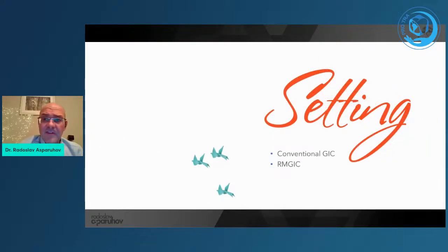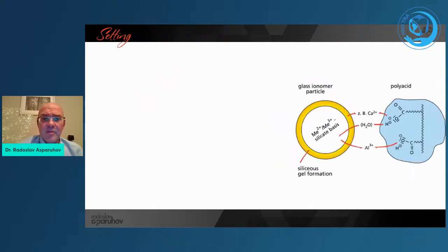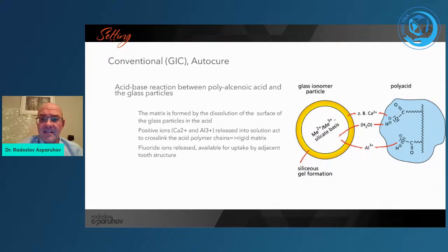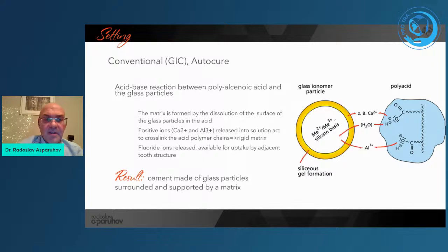The setting reaction is a little bit different for conventional glass ionomer cement than for resin-modified glass ionomer, but with conventional glass ionomers, basically the matrix is formed by the dissolution of the surface of the glass particle in the acid, and the positive ions, calcium and aluminium, are released into the solution and act as a crosslink with the acid polymer to form a rigid matrix. Fluoride ions that are released are available for uptake on the adjacent tooth structure, and then they protect not only the tooth that carries the restoration, but also the adjacent tooth. As a result, we have a cement that is made of glass particles surrounded and supported by a rigid matrix.